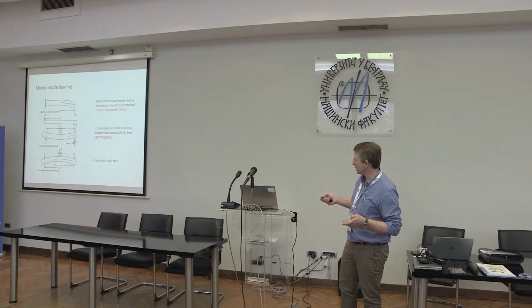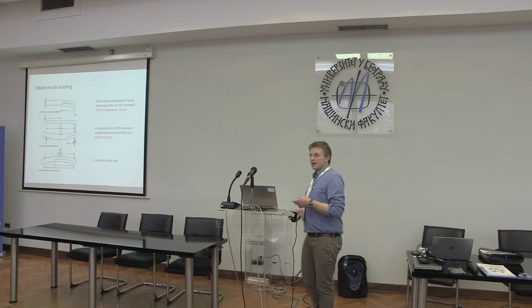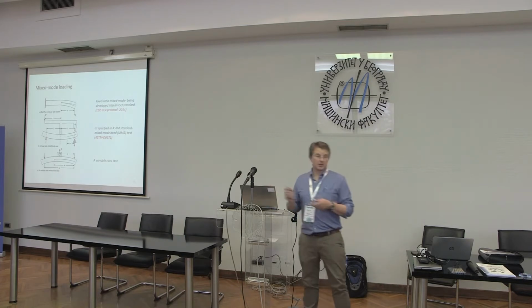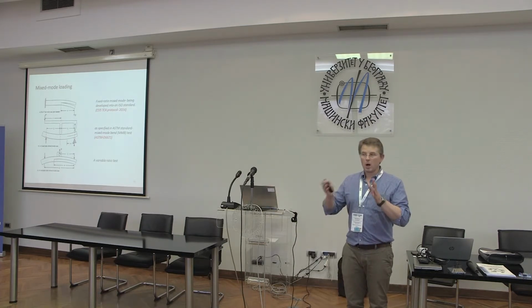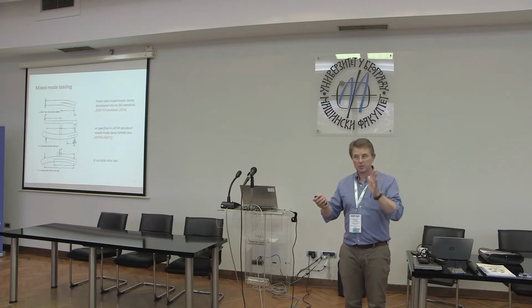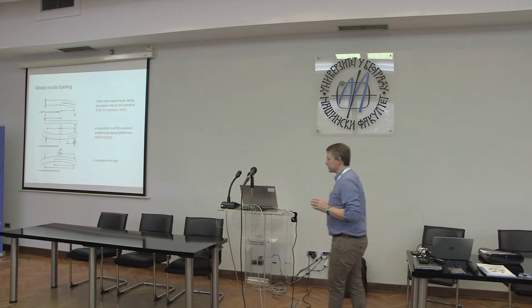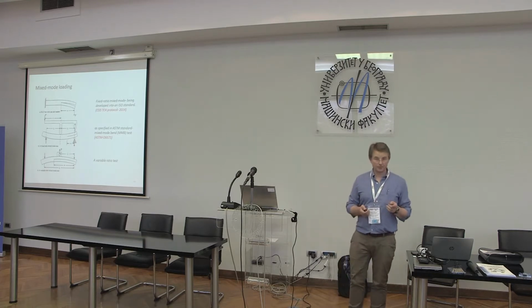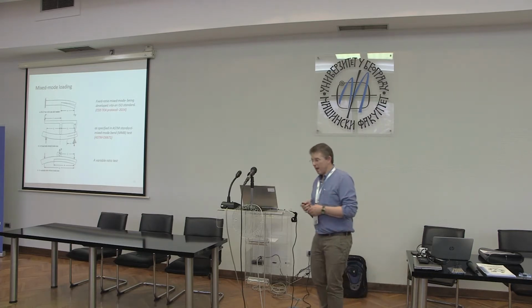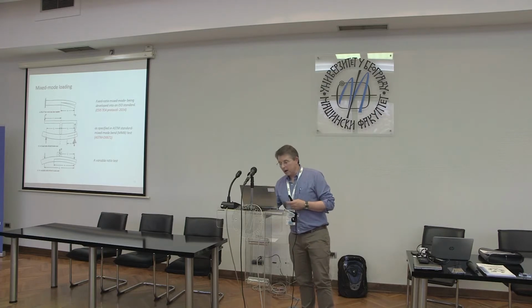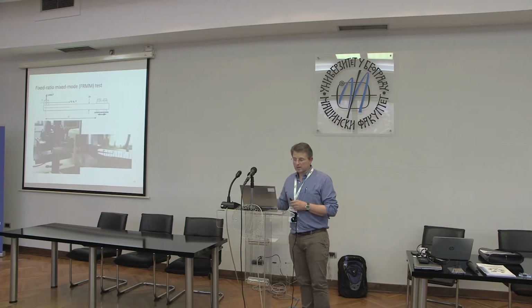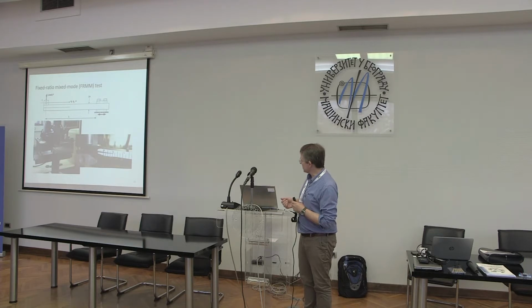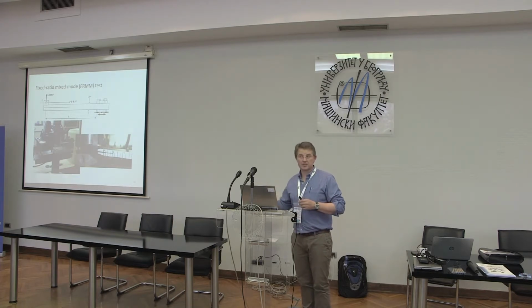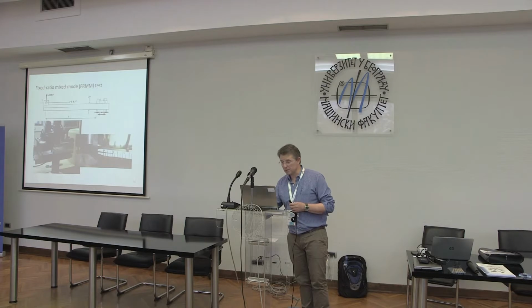The apparatus is more complicated, but it has the advantage that you can generate a complete failure locus, i.e. you can adjust the lever arms to get many different ratios of mode 1 to mode 2. So it's quite versatile. And there are other ways of doing it. I want to just very quickly show you our fixed ratio mixed mode experiment. There's a composite. The top arm is being loaded, the bottom arm is not loaded. The other end of the specimen is clamped in exactly the same way as we would clamp for mode 2.